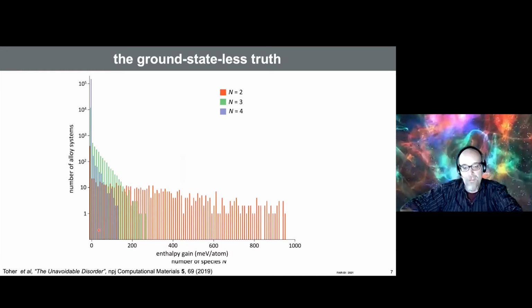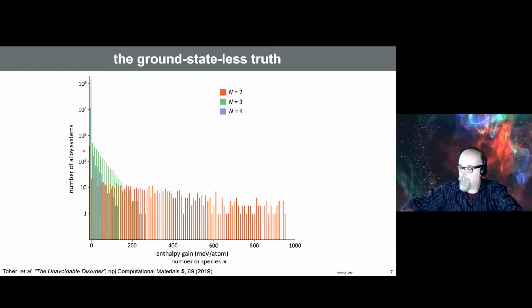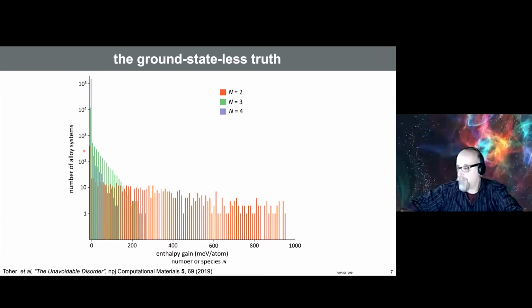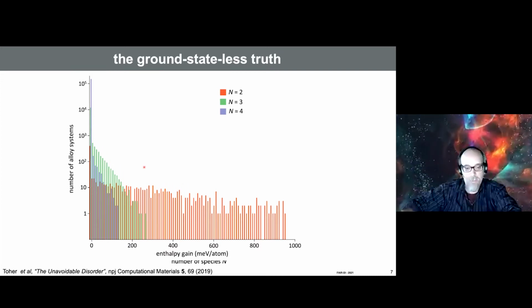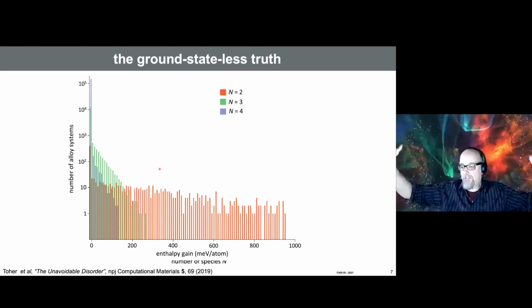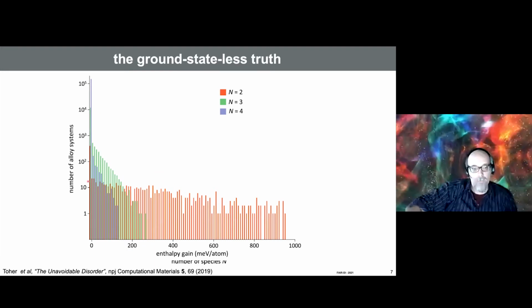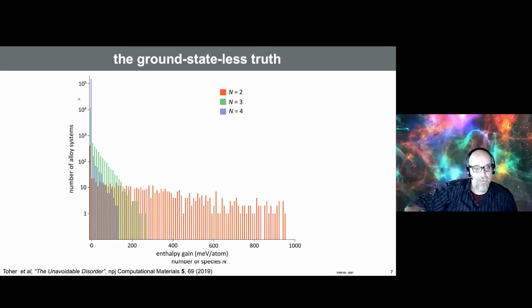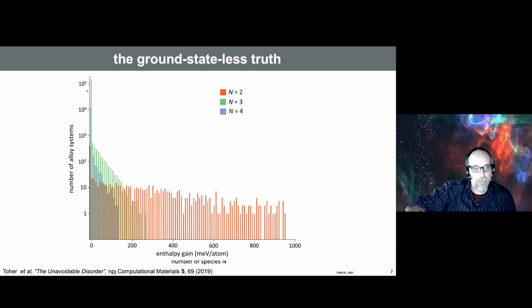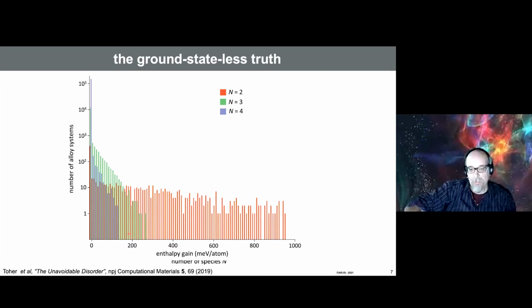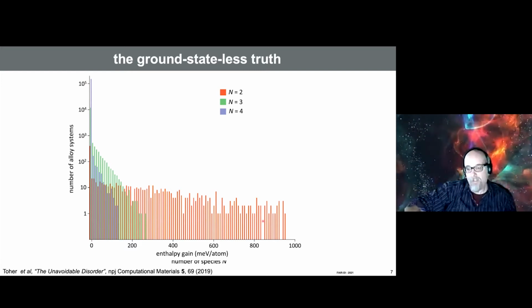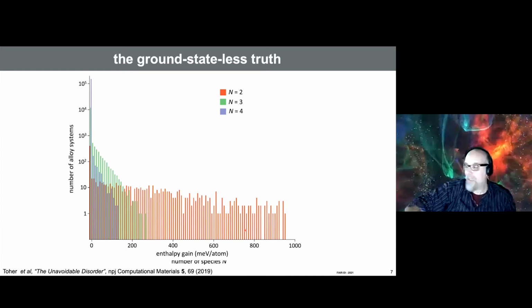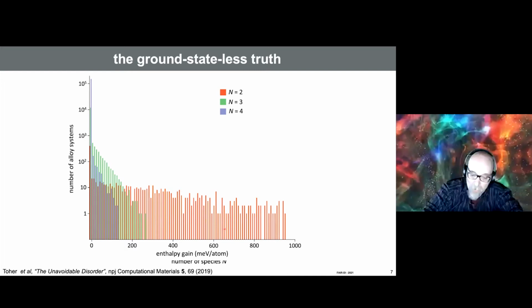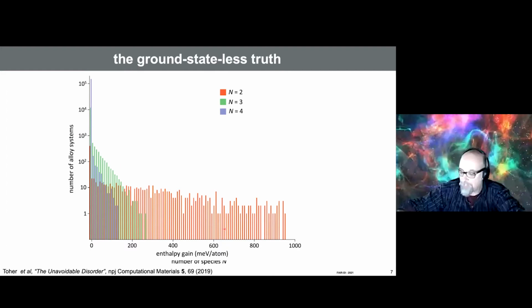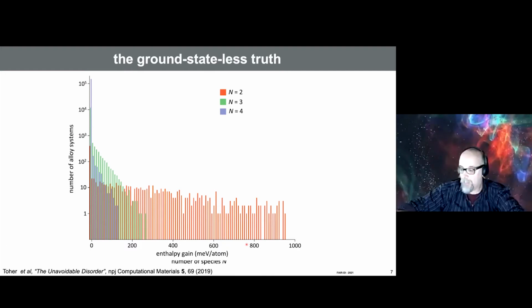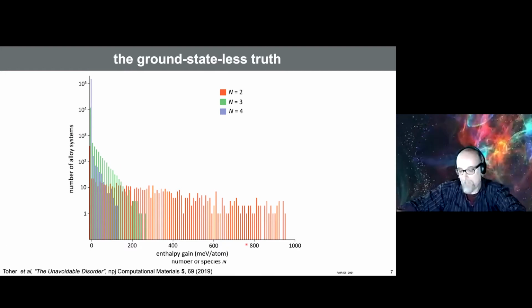So you see that even if the number of configurations increases exponentially because you have more species, so you can arrange them in more ways, their delta shrinks dramatically. So when you do the convolution between the number of alloy systems, which grows exponentially, you see, this is a log plot with the histogram of the enthalpy gain, you see why you have a flattening of your stability toward disorder, and that's why it's pretty much hopeless to look for ordered systems at many species.